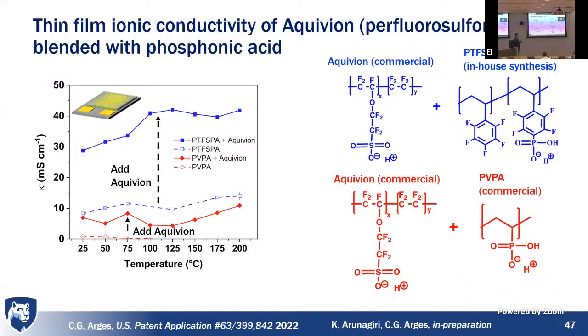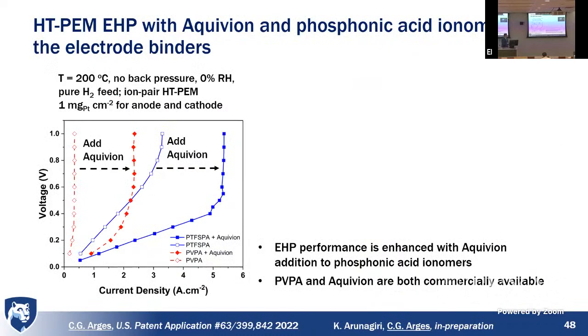Could we take a commercial material off the shelf and get the same thing? And we do, we see it, right? If we take polyvinyl phosphonic acid, we add Aquivion, we see the conductivity jump up, but the conductivity is not as good. So we made an MEA. We tested the fuel cell performance. So here, the red lines, right? This is that PVPA that's really bad, right? We try to pull current and the voltage just plummets. It's no good. We add a little Aquivion to this commercial polyvinyl phosphonic acid.